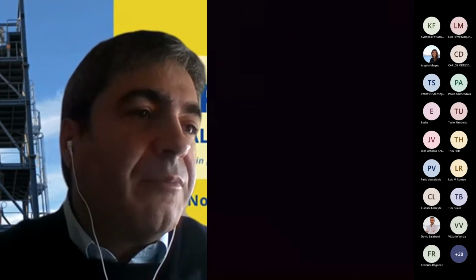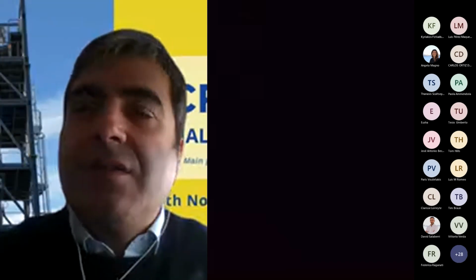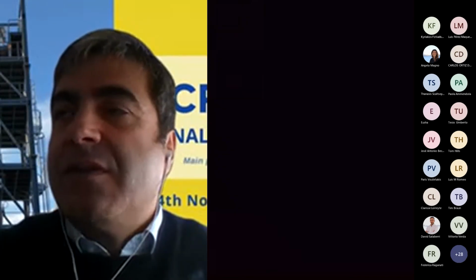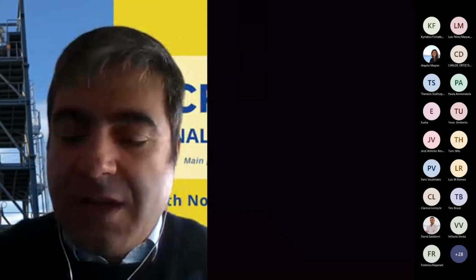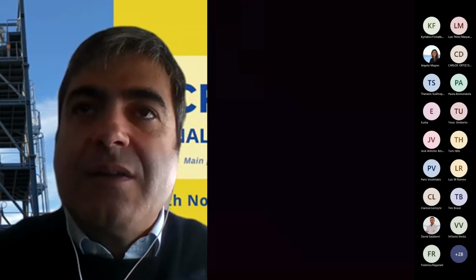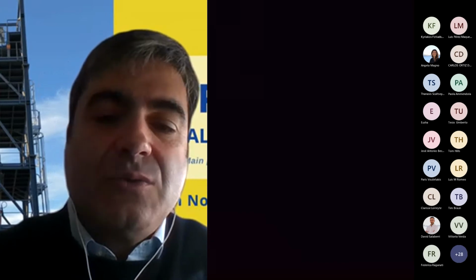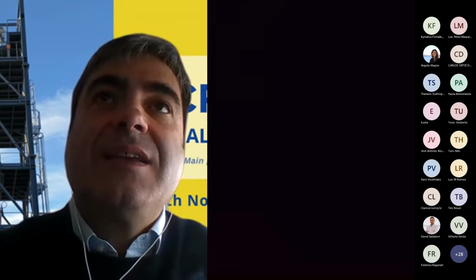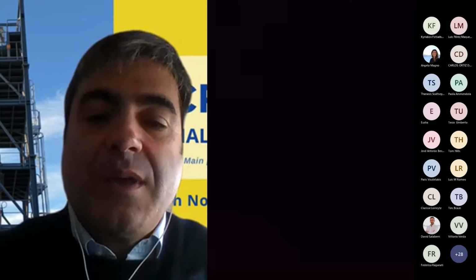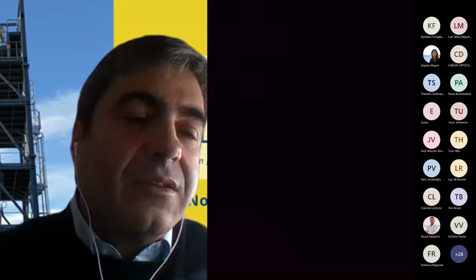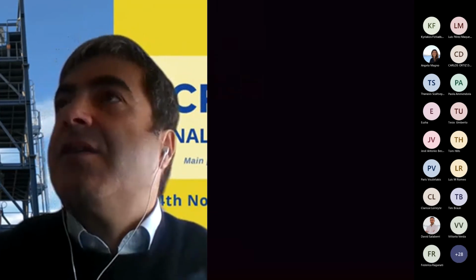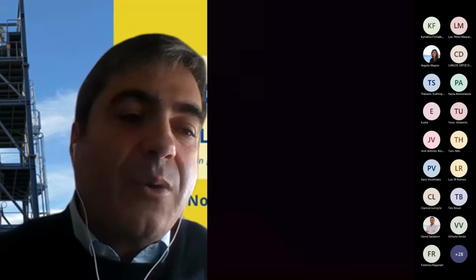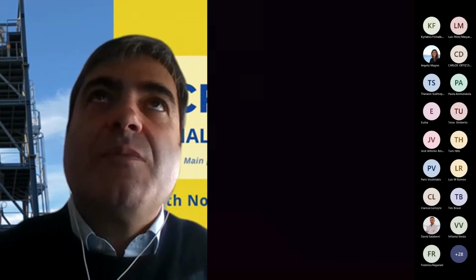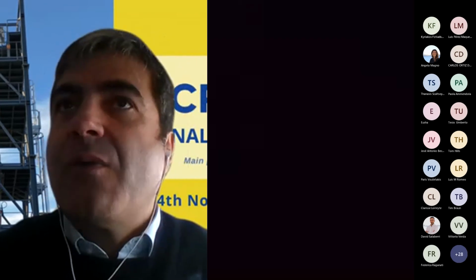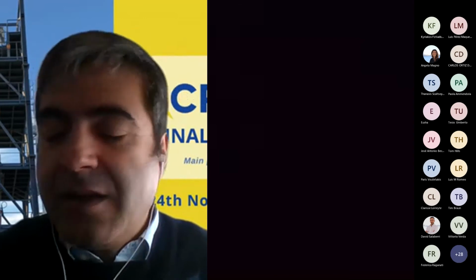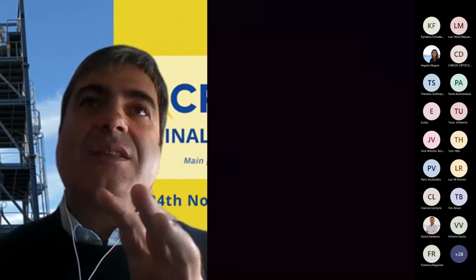If no one has any questions, just let me make some remarks to summarize what we have seen. We have seen in this presentation new knowledge about the effect of the different conditions that could happen inside the reactors, inside the processes. They are new, and we have seen very interesting results related to the effect of temperatures on the carbonation and the calcination and in the global process. We have seen that after the experiments presented here by the members of the consortium, the effect of using sound and using steam clearly improves the potential of application, with very relevant results related to the decrease of temperatures, one of the challenges that we had, and regarding the modeling of the performance in the calcination and the carbonation, and the potential effect in the design of components.